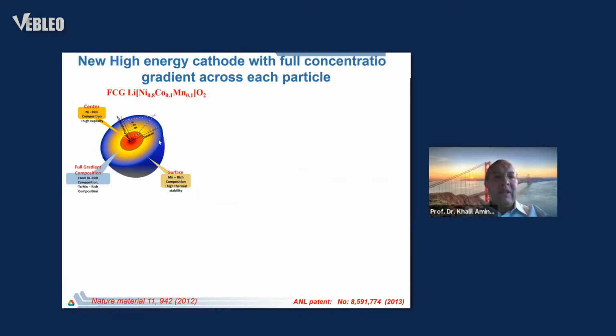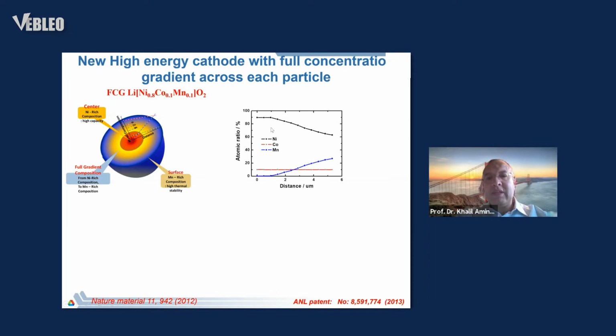So we know that nickel rich causes reactivity. I've shown you the data, the interfacial resistance goes up. So what we did here, we developed a process where we can bury the nickel in the bulk and slowly reduce the nickel and increase the manganese to get stability at the surface, so we can operate at high voltage. Manganese is very stable. This is a EPMA that shows that the nickel is going down, the manganese is going up. We keep the cobalt constant.